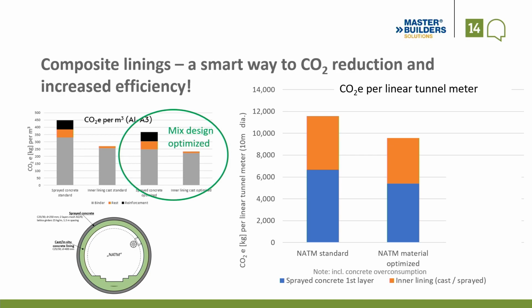The NATM standard is the left-hand side, the sprayed concrete, not improved mix designs. You land on nearly 12 tons CO2 for the structural support per linear meter, out of which the blue part is the sprayed concrete first layer, and the brownish part is the cast concrete. So I have to add some more statements to the numbers. If you do the mathematics yourself, you will get lower numbers.